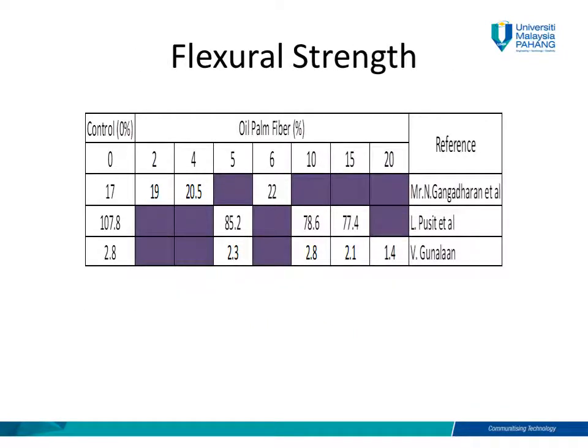Okay, next is the flexural strength of the oil palm fiber. For the first researcher, Mr. N. Gagandharan has 3 replacements, and his replacements show an increasing trend from 19 to 22, higher than the control one. The second is L. Pusit, who has 3 replacements, which is 5, 10, and 15, but her replacements show a decreasing trend from 85.2 to 77.4. And the last one is V. Gunalaan. V. Gunalaan has a decreased trend from 2.3 to 1.4, which is below the control one.